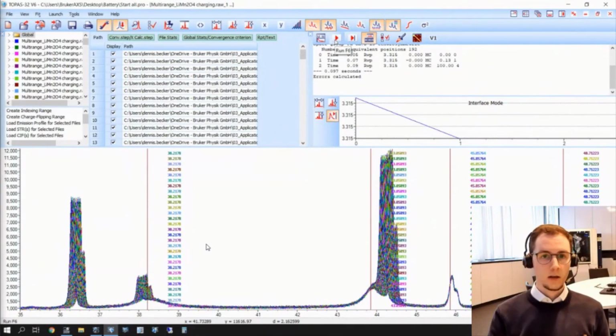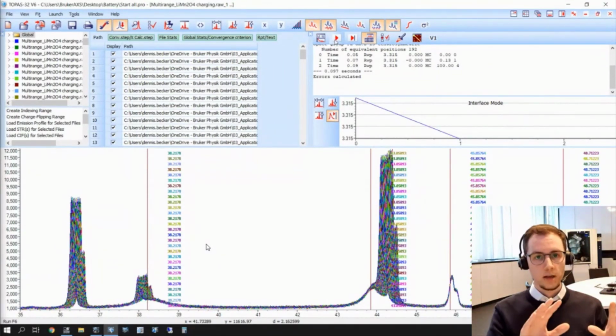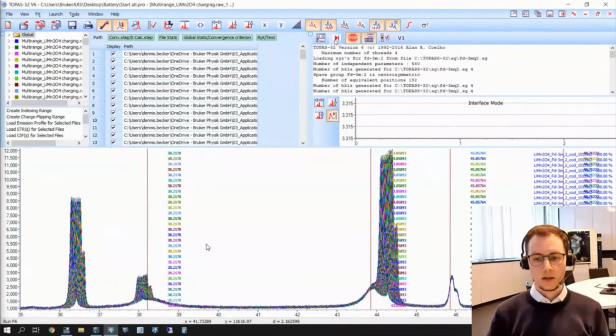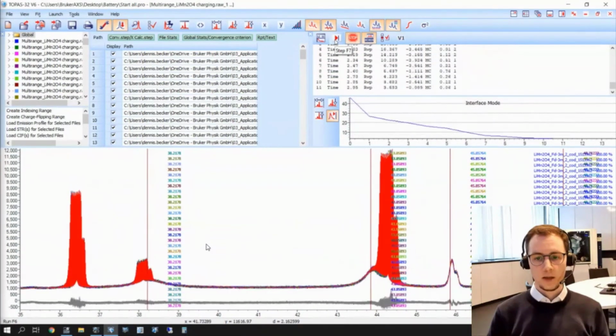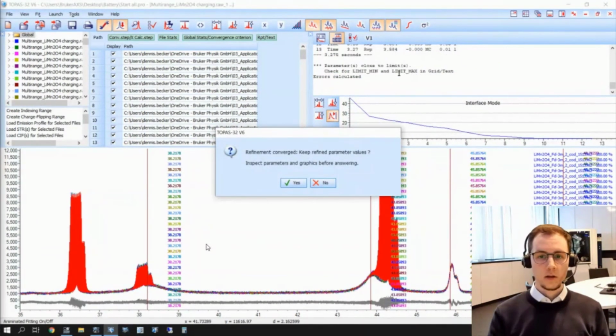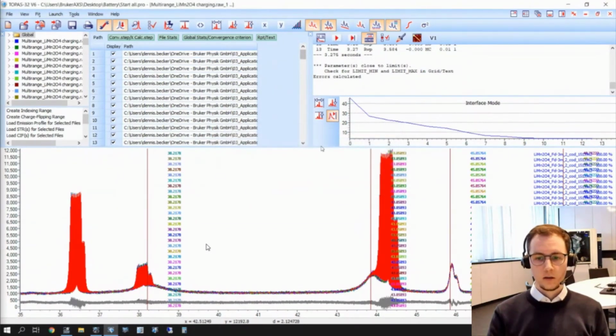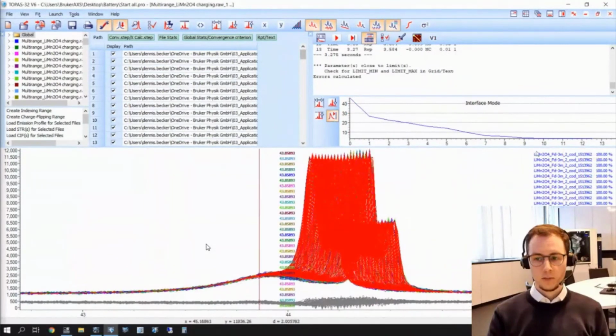I click here, I take the initial model, and TOPAS will calculate the shift and the lattice parameter for all subsequent scans. Let's have a look. And it applies it here. And this took about 3 seconds. On a faster PC, this will, of course, go really even faster, but I think 3 seconds is quite acceptable for fitting of 140 ranges in parallel. Let's zoom in on one of the reflections here, maybe. And you can see for every single range how the reflections have shifted.